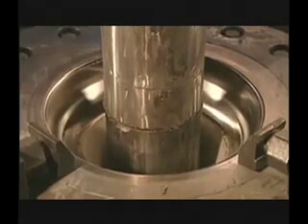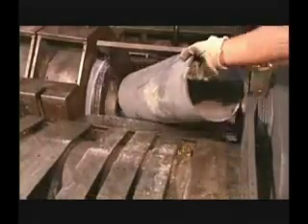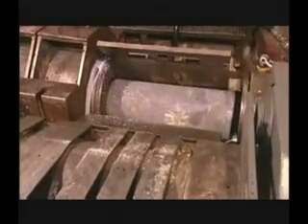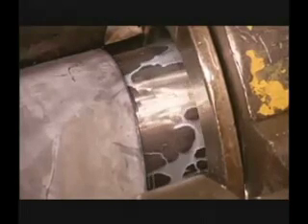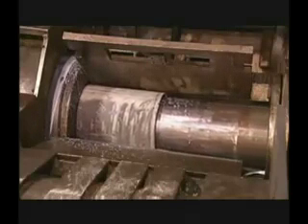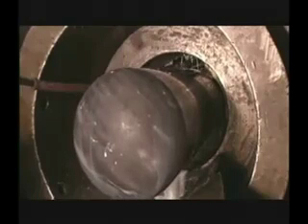After the cup exits the last ironing die, stripper jaws are engaged to remove the cup from the mandrel. After annealing, cleaning, and relubrication operations, first draw cups and secondary cups are processed through the final draw. This press utilizes up to 250 tons of force. Since draw rates are relatively quick, a flood-type coolant is used to prevent overheating.